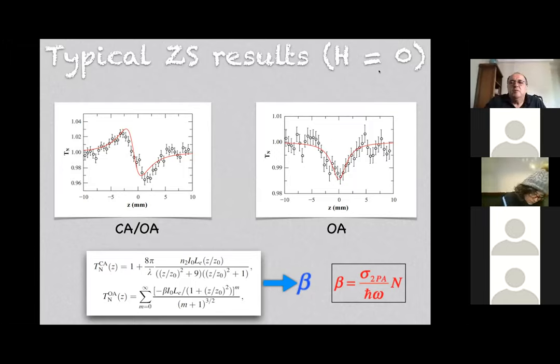So this, for H equal to zero, without the magnetic field, is the typical Z-scan measurement. It is related, as I told you, to n2, which is the nonlinear index of refraction. And this is the typical absorption, normalized transmittance as a function of the Z position. Here also we have just one fitting parameter, n2, and here also one fitting parameter, which is beta. And beta will give us the two-photon absorption cross section sigma.